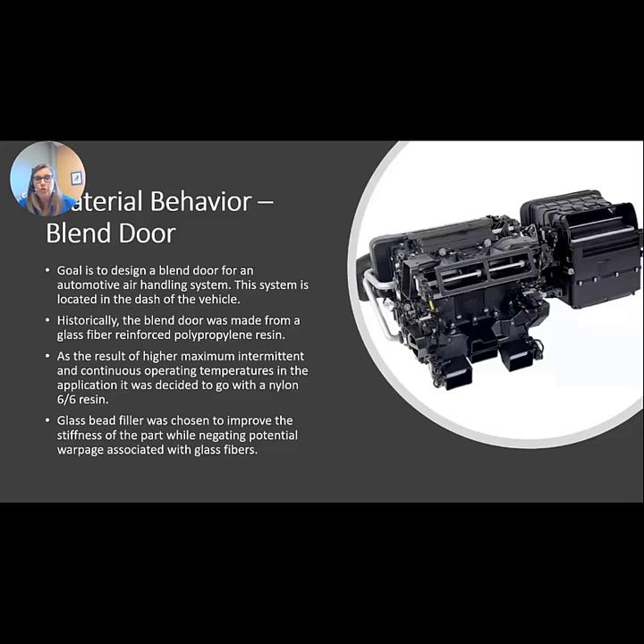So everything is trying to get miniaturized, and as things miniaturize, it generates more heat. So in this application, this new model, they were seeing higher temperatures in the case and in the blend door location. So they decided to go with a more heat resistant material, which was a nylon 6,6 resin. The other change they made was they got rid of the glass fiber and opted for a glass bead filler in order to get rid of some of the warpage issues they've seen in the past with using glass fibers in this application.